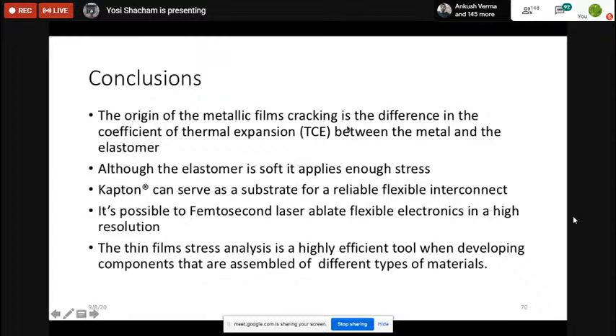And the origin of the metal film cracking is the difference in the coefficient of thermal expansion. Also, the elastomer is soft, yet it applies enough stress, and Kapton can serve as a substrate for flexible interconnects. And a combination can be a Kapton substrate, and then on top of it PDMS and then metal. And femtosecond laser ablation is a good technology. And thin film stress analysis is a very efficient tool when developing components that are assembled of different types of materials.